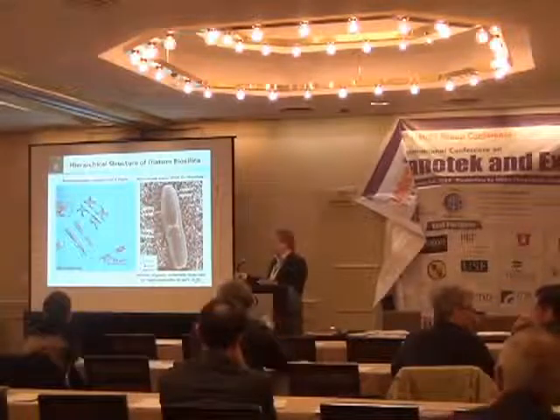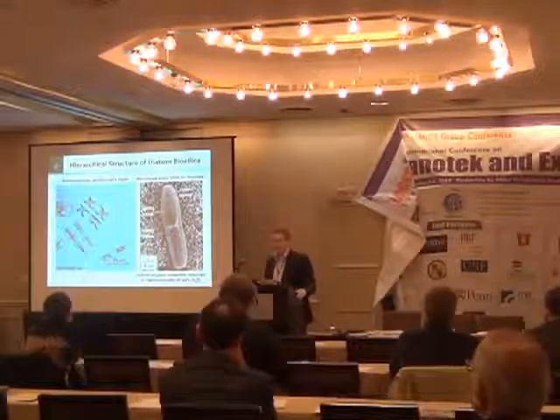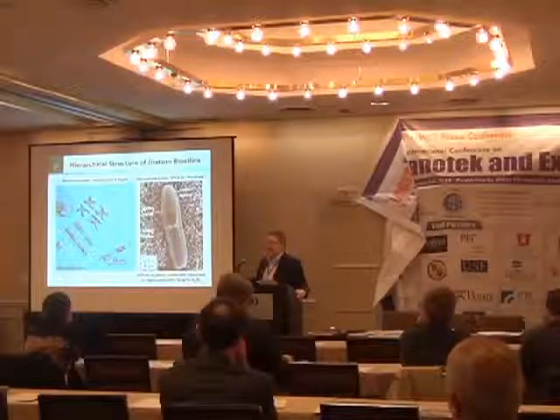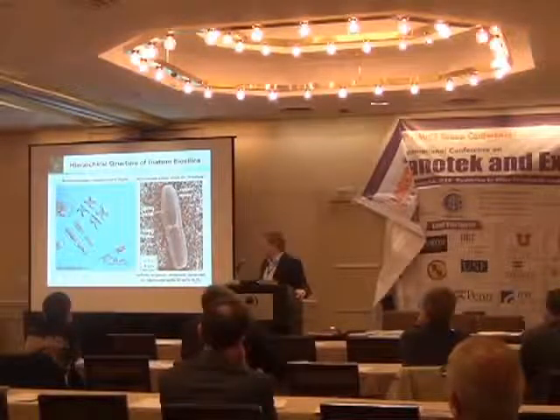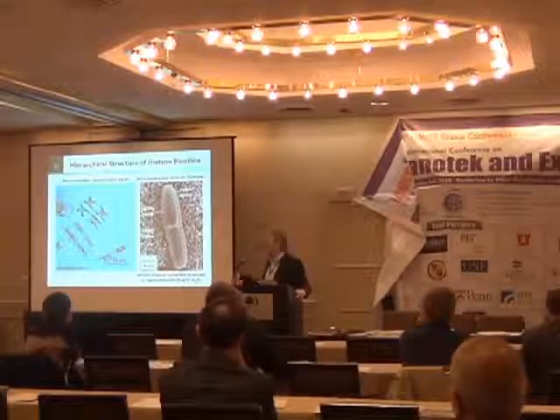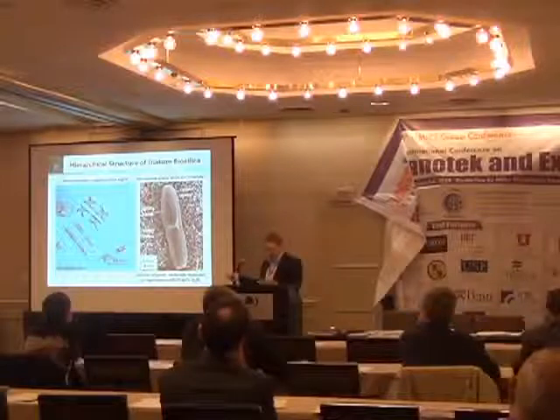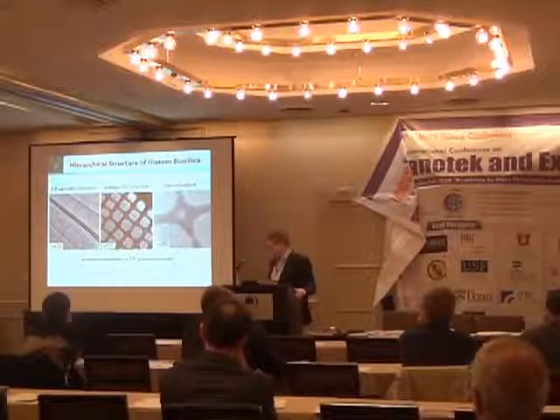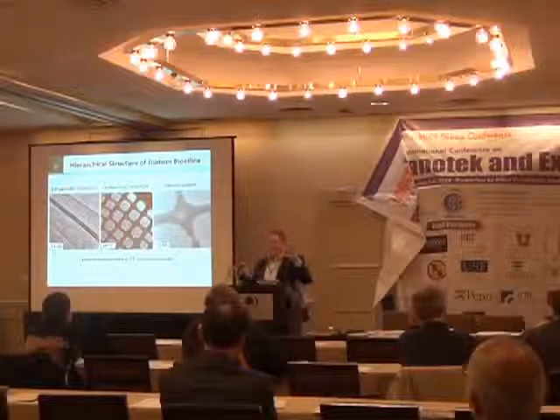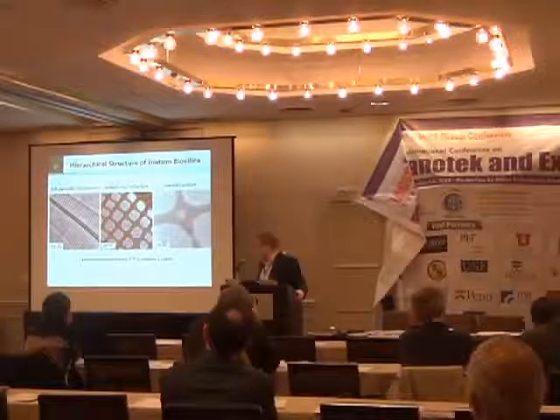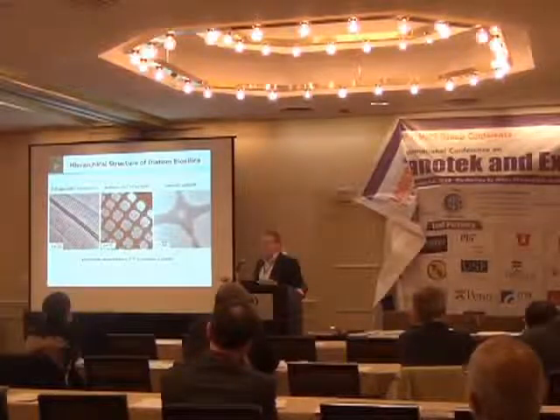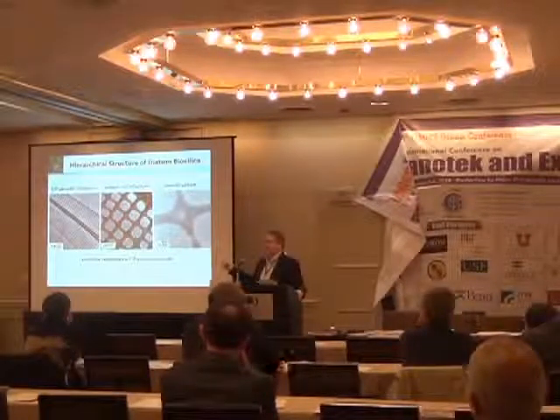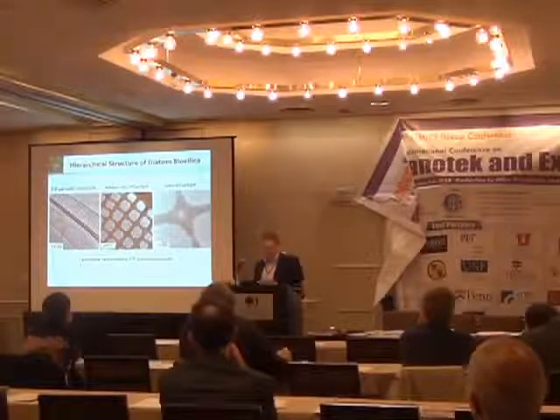Here's a picture of the living organism. The green material is the chlorophyll contained in the chloroplast. The outer feature is actually composed of glass, so it's transparent under a light microscope. But if you remove those cellular materials, you expose this intricate nanostructure. It's hierarchical — at increasingly higher magnifications, you see at the submicron scale a very ordered lattice that resembles a photonic crystal array, with fine structures embedded within it at scale features below 10 nanometers.